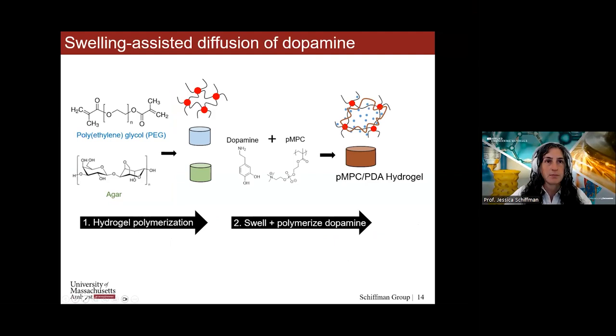So in one particular example from our group, we were really interested in hydrogels used as wound dressings that repel bacteria. So here we took two different gels: polyethylene glycol, an already very fouling-resistant material, and agar. Agar is literally what we feed our bacteria to keep them alive. So you can imagine that agar gels foul very readily with bacteria. We made these materials into hydrogels, and then during the swelling to give it its final shape, right? It's a hydrogel, it loves water. During that swelling, we can diffuse in dopamine, which again, we hoped would carry our polymer zwitterion along for the ride. On the right, I show our final gel is brown because we know that dopamine polymerization has a characteristic brown color.